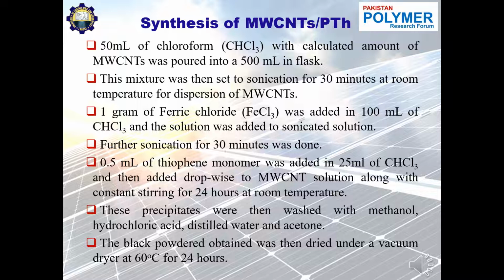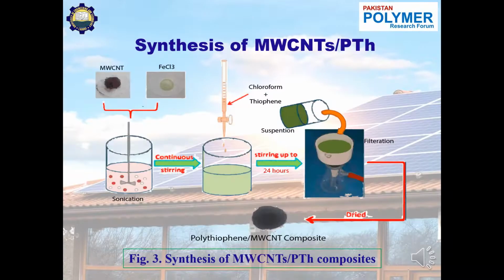After this, 0.5 ml solution of thiophene monomer was made in 25 ml of chloroform and then added dropwise with the help of a burette to the MWCNT solution along with constant stirring for 24 hours at room temperature. The precipitates obtained after 24 hours were then washed with methanol, hydrochloric acid, and a distilled water and acetone mixture. After the washing, the black precipitates obtained were dried in a vacuum oven at 60 degrees Celsius for 24 hours, and a black powder of synthesized nanocomposite was obtained. Here in this diagram, you can see the complete step-by-step process of synthesis of multi-wall carbon nanotube and polythiophene-based nanocomposite.